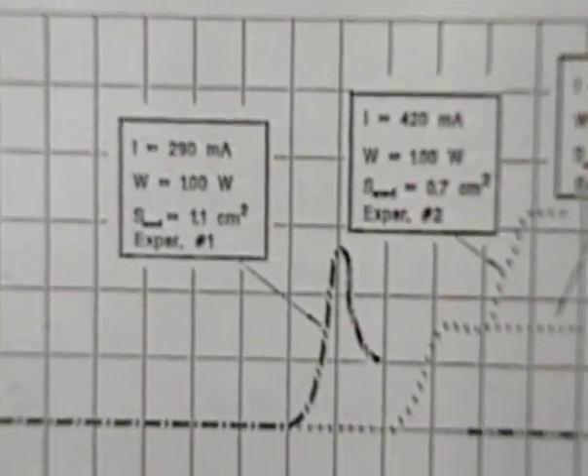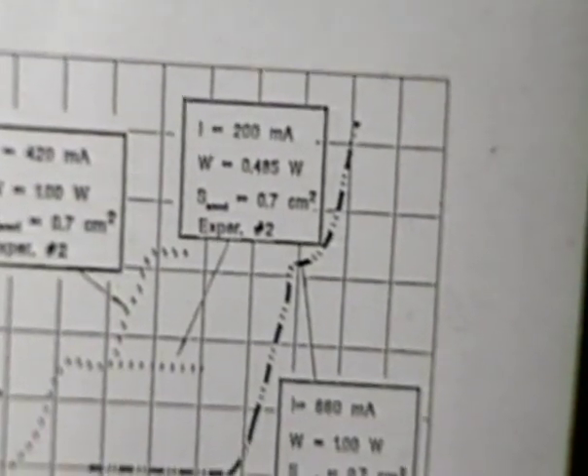However, we didn't register any neutron emissions anymore. In our best achievement, the heat excess was about 10%. We didn't get more than this. So we believe these experiments verify that molten salts are perspective, and that the results which Dr. Liao presented are quite reliable. So that's all I have to say.